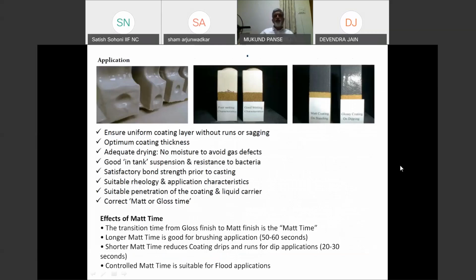While coating, we have to ensure in dip coating that a uniform layer is applied. The optimum coating thickness depends on your requirement, the metal you are pouring and the thickness of metal around the core or mold. There is no moisture left. There is good suspension in the tank and resistance to bacteria formation. Satisfactory bond strength, suitable rheology and application. Rheology is suspension only, and application characteristics.